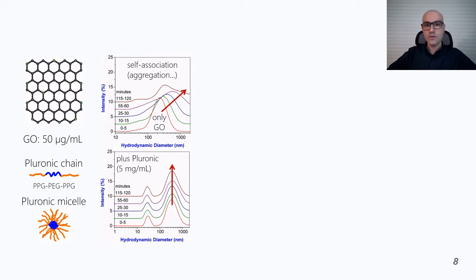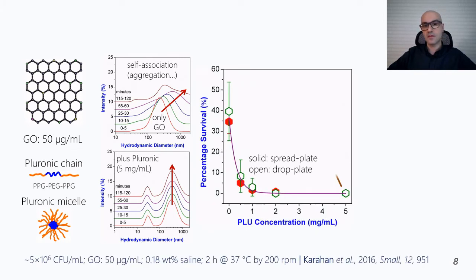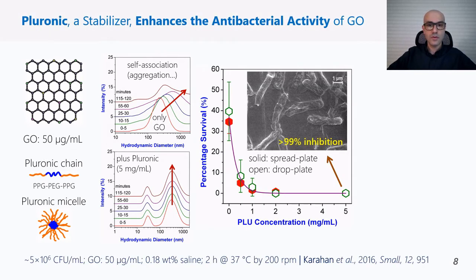But we also observed something a bit unexpected. As we increase the pluronic concentration, the antibacterial activity of graphene oxide boosted. This exciting observation is likely because of the combination of the increased colloidal stability of graphene oxide and the osmotic pressure of polymers on the cells.